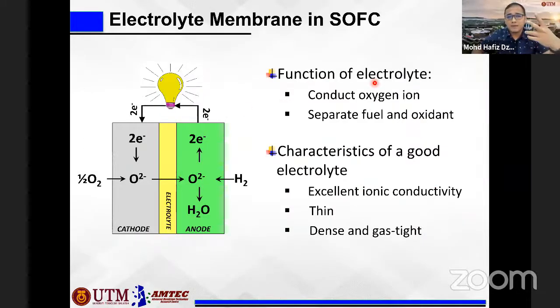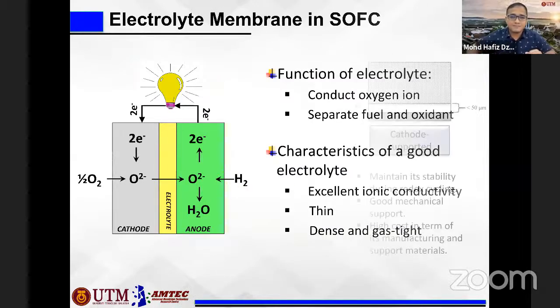So the main function of the electrolyte is that it has to be ion conductive, and also it has to act as the separator between the fuel in the anode and the oxidant in the cathode. And the characteristics of a good electrolyte, which we normally also call a membrane: it has to have excellent ion conductivity. It has to be thin, and also it has to be dense and gas tight, so that the gases from both anode and cathode will not mix together. Therefore, it must be gas tight and dense.